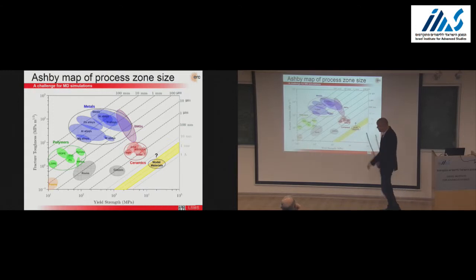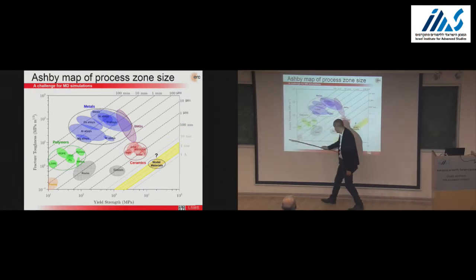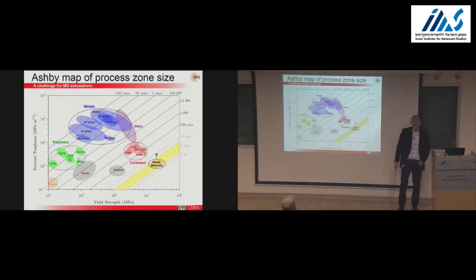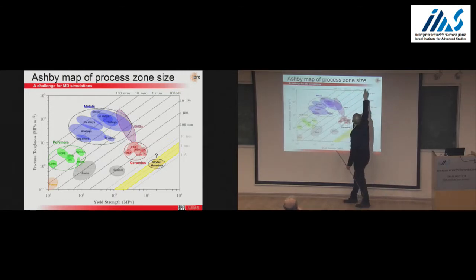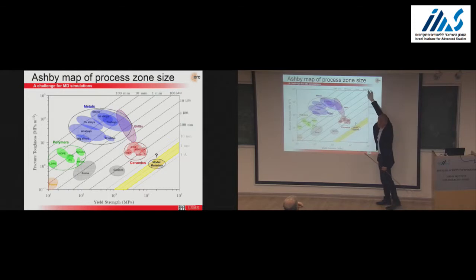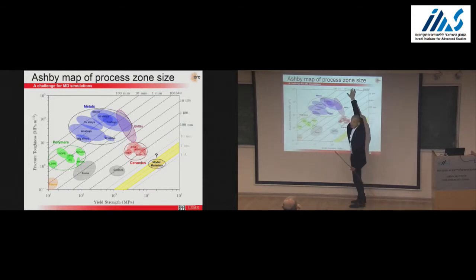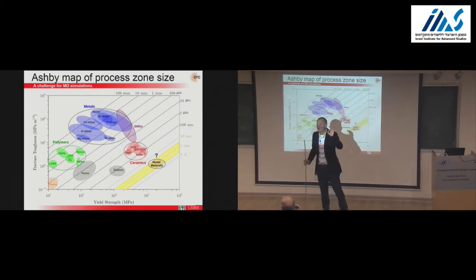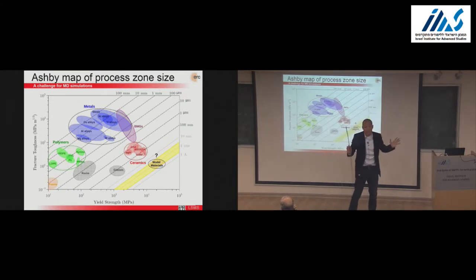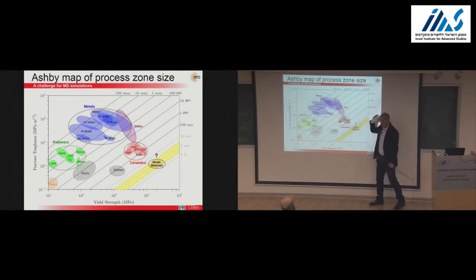So this is an Ashby map of fracture toughness versus yield strength. You can estimate the process zone size at a crack tip as the ratio of the fracture toughness to the yield strength, squared. You see it revealed here with those oblique lines, with those values. For metals, it's big, millimeter sizes. The record MD simulations you can hope to do is basically a micrometer cube, so we are way too big compared to molecular dynamics. Ceramics, 100 nanometers, still big for molecular dynamics.